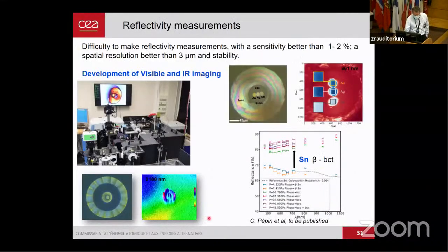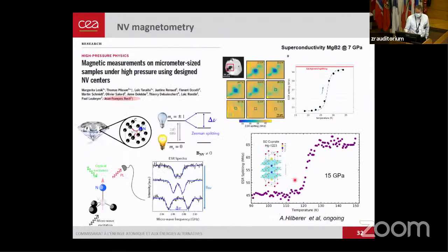With this infrared in the 2.1 micron range, which should be needed for the measurements of the superconductivity, we have a spatial resolution that allows us to see the very small sample of hydrogen, not at very high pressure, but still. And these measurements of reflectivity are accurate. We can even see a change of reflectivity at the phase transition on tin. Then NV magnetometry is another example, where we are collaborating with Jean-François Roch, who is pushing for that.